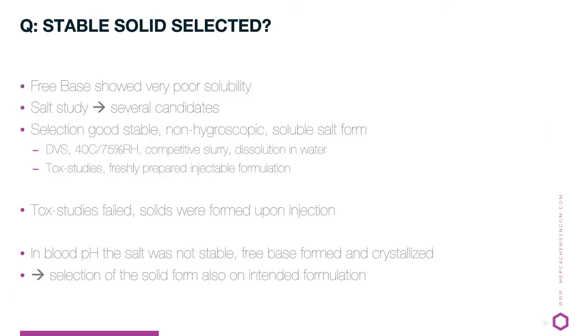Finally, two examples. If a stable form, a good solid, was selected. That's the case here in which a free base showed only a poor solubility. We did a salt study and there were several candidates. From that we had a good stable, non-hygroscopic and very soluble salt form. Based on solid state properties, a very good material. Production, a very good material.